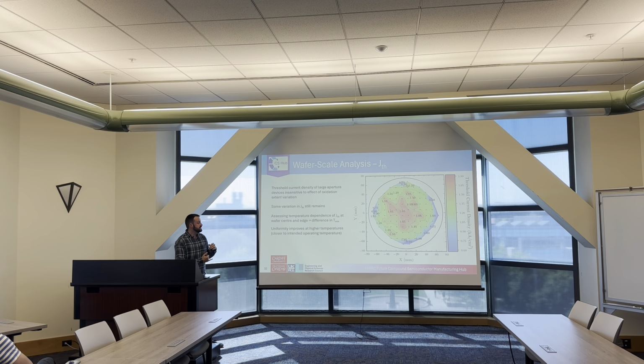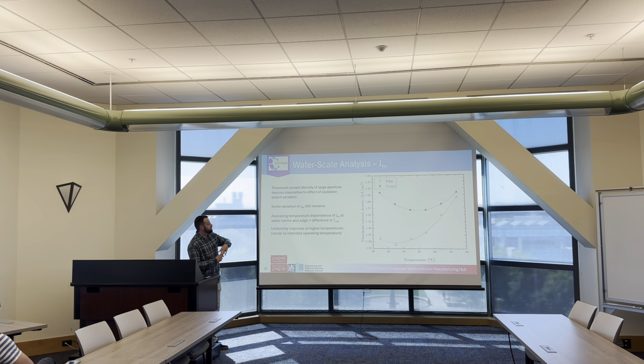If we assess the temperature dependence of the threshold current density at various locations on the wafer, we get plots like this. So the black triangles for the center, white triangles for the edge. It's clear that there's a difference in the temperature that corresponds to the minimum of the threshold current density versus temperature plot.